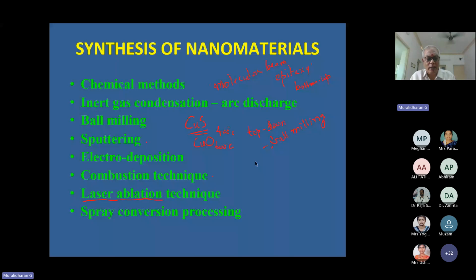Whereas some materials have a tendency to dissociate. For example, when you take gallium arsenide, if you melt it and keep it in the molten state for a good amount of time in open atmosphere, gallium will leave the gallium arsenide, making the melt non-stoichiometric. For every arsenic atom, one gallium would have existed initially, but now the number of gallium atoms per arsenic would have come down. It may be something like for every 100 arsenic, only 90 gallium will be there. For such things, people use a laser ablation technique.